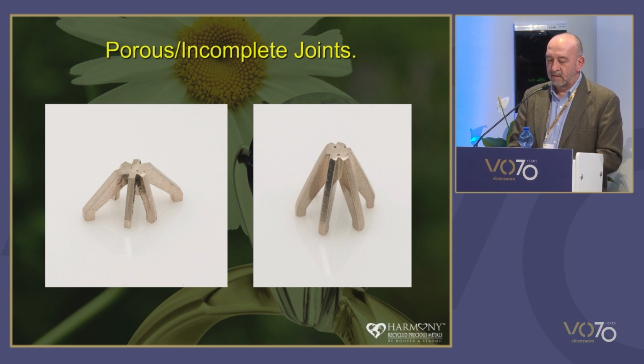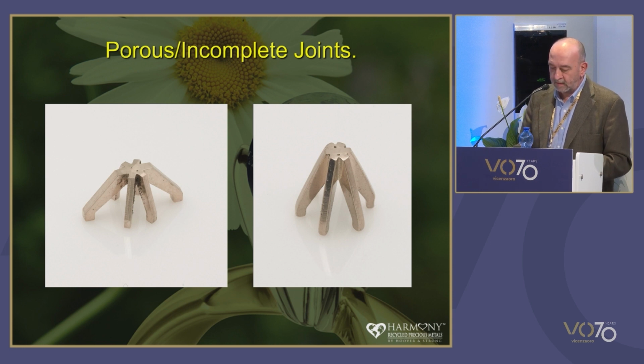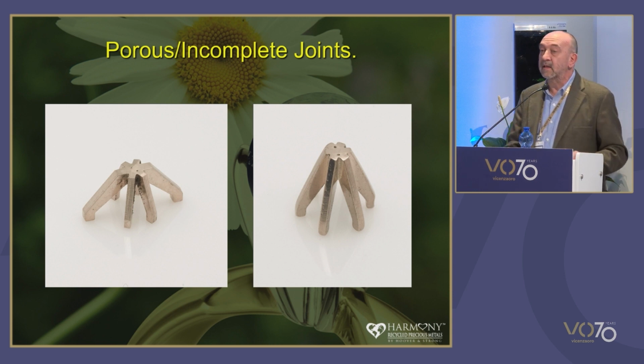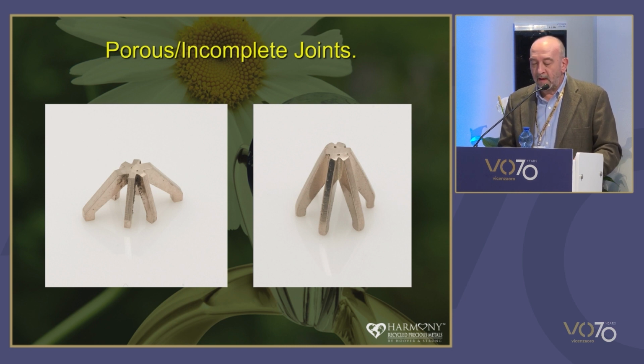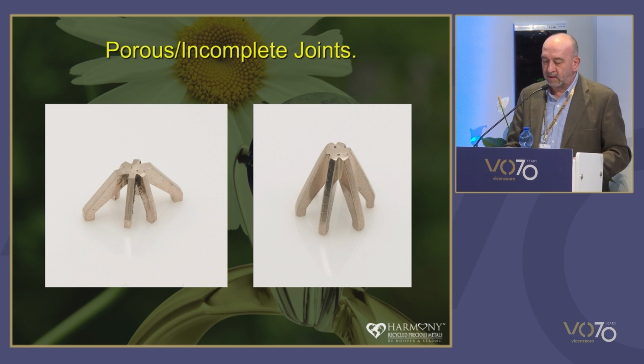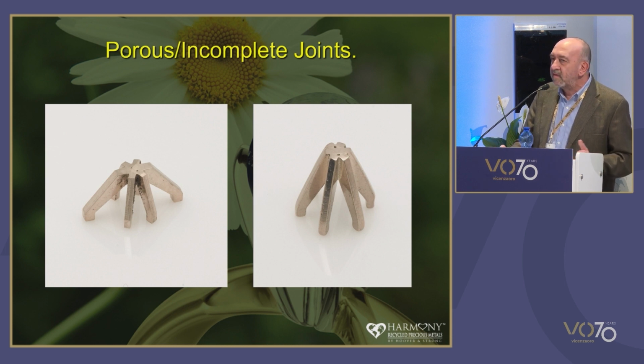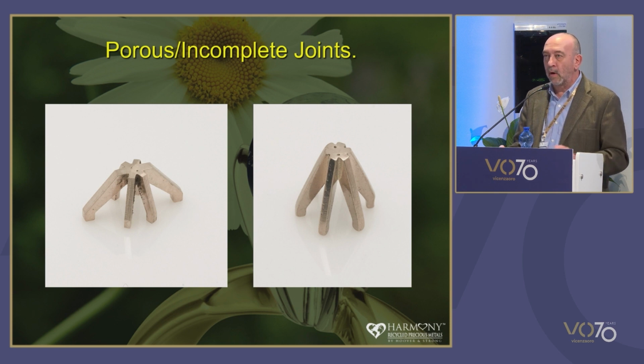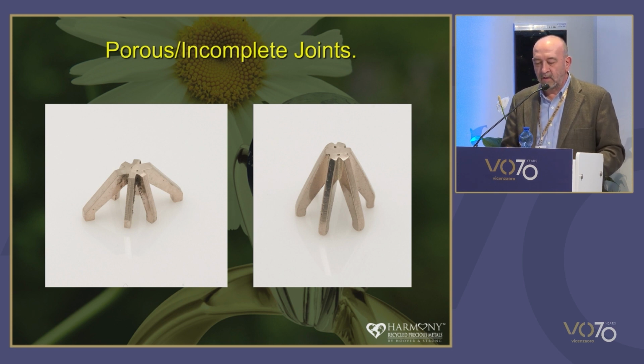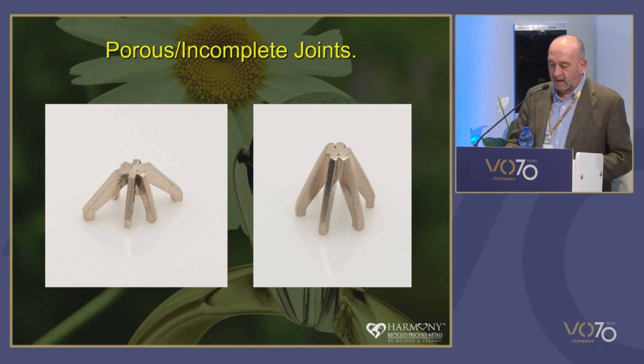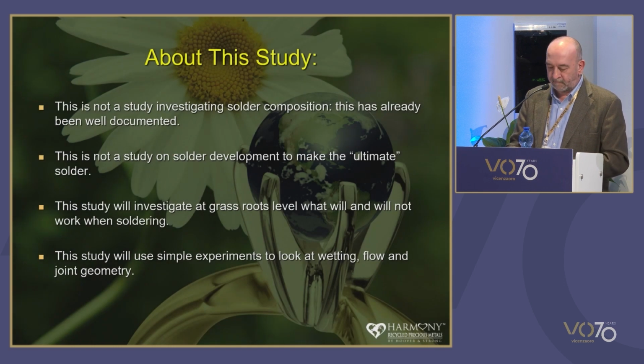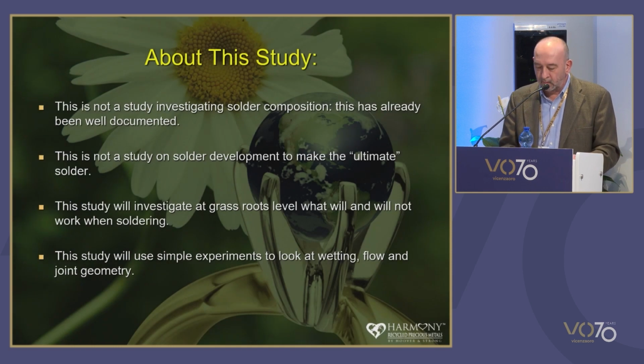And after starting this study, the type of defect started to occur in several other head shank combinations using different solders. So it became obvious this investigation needed to go deeper. It also became apparent very quickly that the scope of the investigation was going to be huge. We stock 50, maybe 60 different types of solder, and so to examine and characterize all of our solders was going to be a very large task indeed, so we needed to focus a little bit more. So really, what this study is about is, it's not a study on solder compositions.